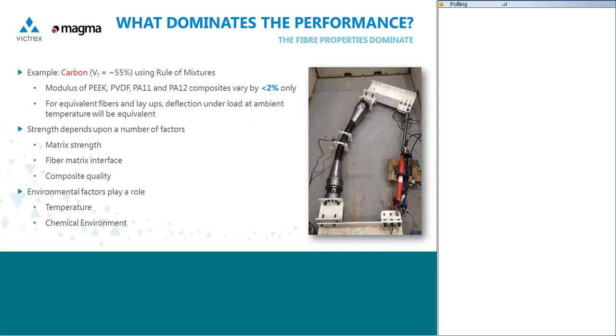So here I just wanted to focus on what dominates the performance of the final pipe itself. And I know Mick will talk more to properties of the pipe a little bit later. But if you consider a 55% volume fraction carbon unidirectional composite, then most people will know the rule of mixtures for composites. Basically, this means that the carbon fibers themselves will dominate the properties of the composite, and if you look at the modulus of any 55% carbon reinforced polymer at ambient temperature and with the same layup, then the stiffness is only going to vary by about 2%. So under ambient conditions, you would expect to see extremely similar performance in all of those composite materials.